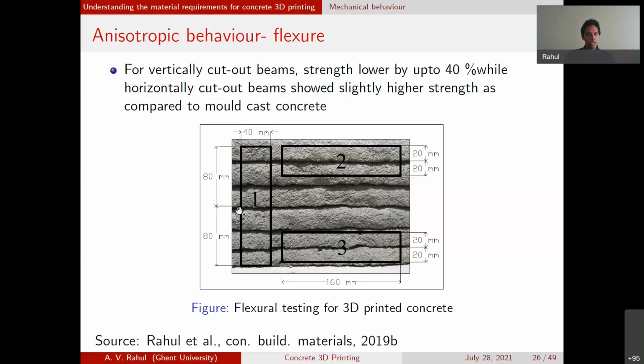But if you consider the same situation here, with a central loading like this, then you have maximum bending stress occurring here, you have a crack existing here, and there's tensile stress existing in this direction. This means that it's easier for the concrete to break under this tensile stress. So you see a much more premature failure in the vertical beam. In fact, if you do the test, we often see about a 40% decrease in this direction as compared to directions 2 and 3. Directions 2 and 3 give comparable results to mold cast samples. That means if you make the same concrete in a mold and test it without any presence of layers, you see that the strength is similar for 2 and 3, similar to the mold cast. In this one, you will see around a 40% decrease in strength.